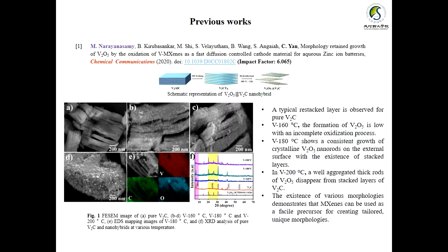I noticed that at 160 degrees centigrade, the formation of V2O5 is very low, with incomplete oxidation. Whereas at 180 degrees centigrade, it shows a consistent growth of crystalline V2O5 nanorods on the external surface, with the existence of stacked layers. At 200 degrees centigrade, well-aggregated thick rods of V2O5 disappear from the stacked layers of V2C, and the existence of various morphologies